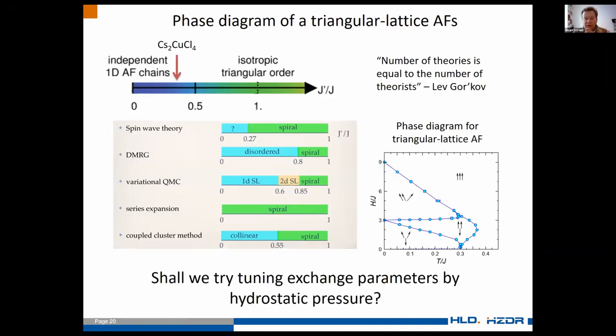If you look at the phase diagram of this system, of these triangular lattice antiferromagnets, you would see different materials. What is important is that you tune the J prime over J parameter, where J and J prime are the interactions on the chains and on the diagonal of the triangular lattice. When you change this J prime over J ratio, you can tune the system from independent one-dimensional antiferromagnetic chains, when the interaction between the chains is zero, to an isotropic triangular order. And somewhere in between, there should be some transition.